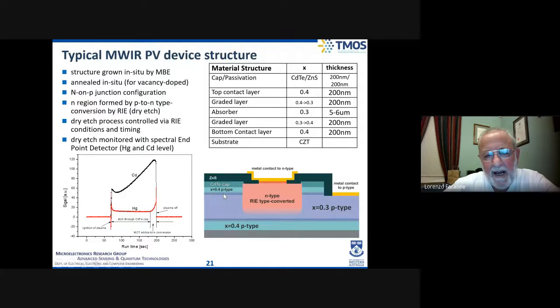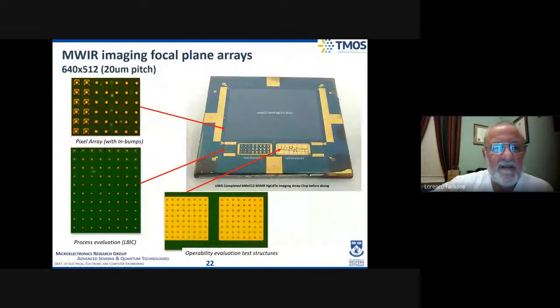We then grow an X equal 0.4 layer at the surface, followed by a cadmium telluride cap. So that whole sequence - 0.3, 0.4, 0.3, 0.4, and essentially 1 for the cad telluride - all of those layers, plus graded layers in between, are grown in a single growth run within the MBE machine. So it's a bit more complicated than just making a diode, although in the end that's really all a photovoltaic detector is - simply a diode, similar to a solar cell.